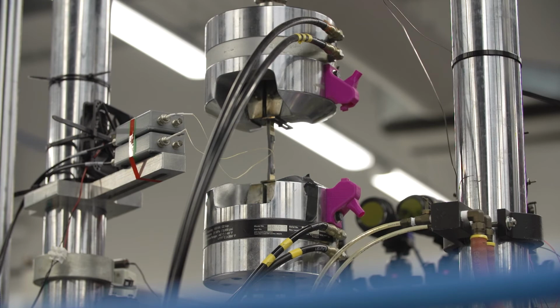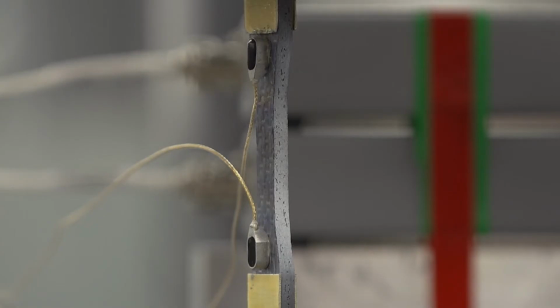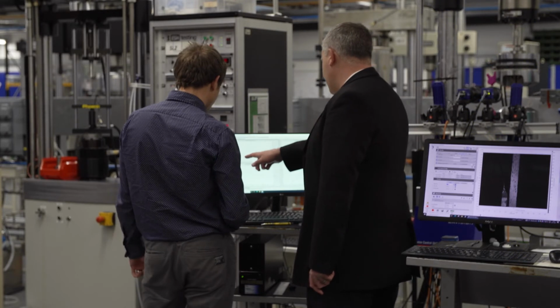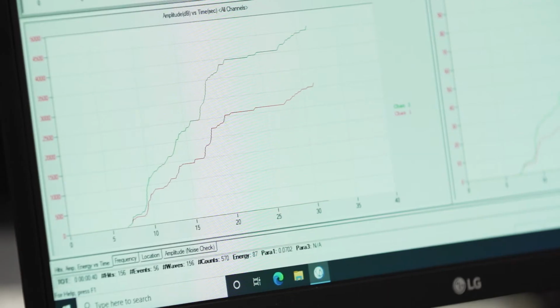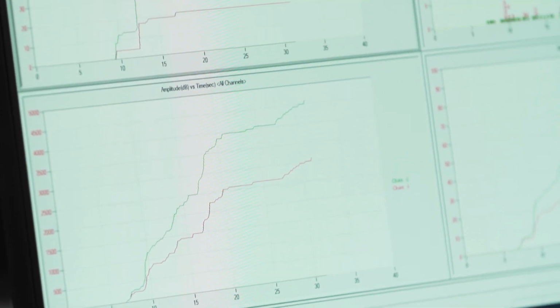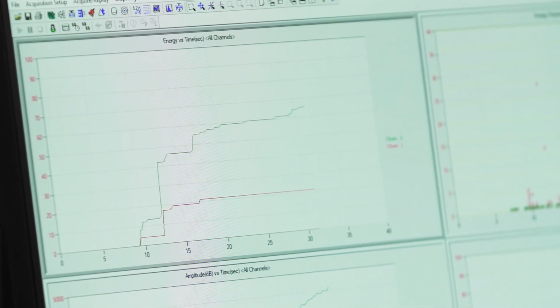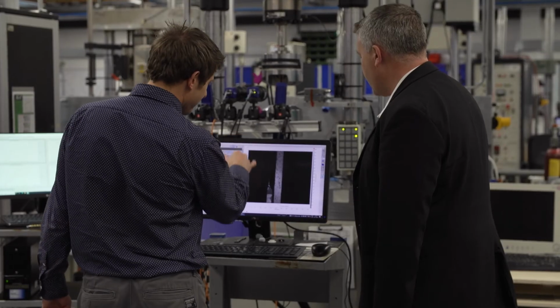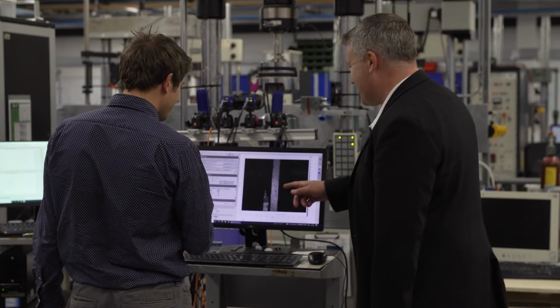So there are a number of advanced techniques we can use on CMCs to understand damage and characterization as we use these materials. For instance, we can use something called acoustic emission, because these materials in nature make noise when they're damaged, and that emits elastic waves, and we can analyze those waves for damage, and then we can sometimes determine what that damage represents, whether it's a matrix crack, fiber failure, interface debonding, and also we can use techniques like XCT or X-ray computed tomography, which will give us an internal map of everything within the materials, and we can use that to understand damage and how damage evolves throughout these materials usage.